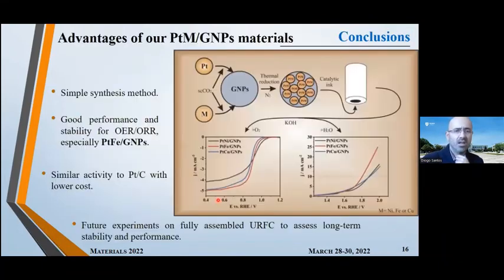So just to summarize the advantages of the materials that we have prepared as bifunctional electrocatalysts for unitized regenerative fuel cells, it's very important that we believe that this simple synthesis method can be a very good approach for the preparation of the materials. As we see here, we followed that preparation, and then we simply, I didn't show before, we simply put the catalyst prepared on the tip of this glassy carbon electrode, then to run the measurements that I just showed. And the materials showed very good performance and stability, both for the oxygen evolution reaction and for the oxygen reduction reaction, especially the platinum iron supported on the graphene nanoplatelets.